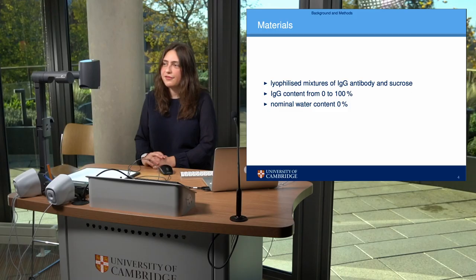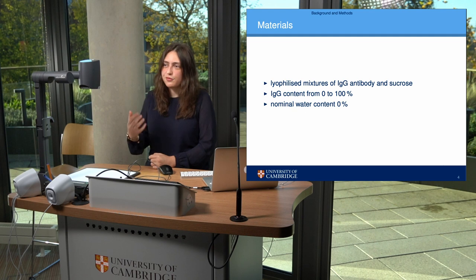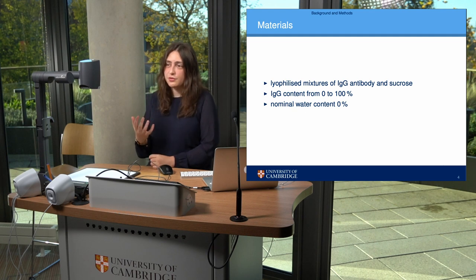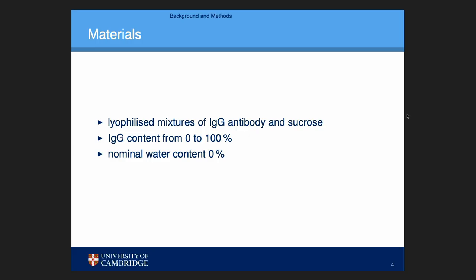We used a very high secondary drying temperature during the freeze drying to make sure that we remove almost all of the water during the drying. This is not commonly done in drug production, but it is done for the purpose of this study.